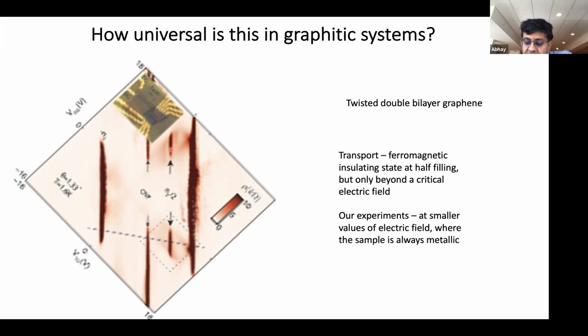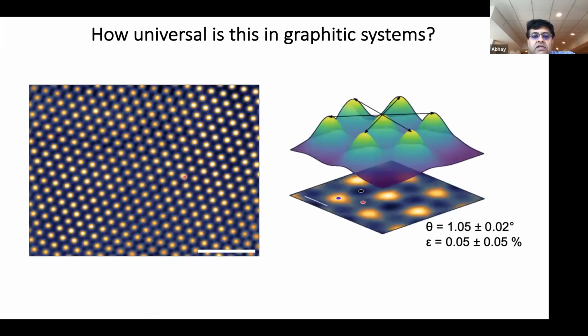So we did a bunch of STM experiments on this material, and we concentrated on electric fields that are quite small. At all electric fields that we measured, the sample is actually metallic. It's not insulating at any of these electric fields, but it's otherwise very much like the transport system. In this sample, for technical reasons, which I can get into if somebody's interested, we were able to make beautifully clean and beautifully large samples on macroscopic, i.e. micron size, length scales. Each of these dots here is not the atomic lattice. Each of these is one Moiré unit cell, which is about 10 nanometers. And so you can see over hundreds of Moiré unit cells, we have a very uniform system.